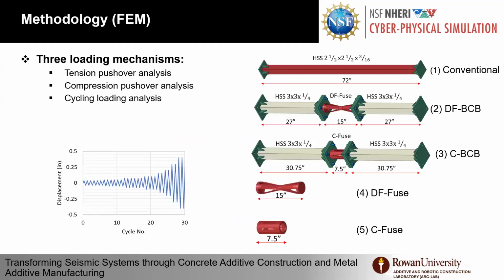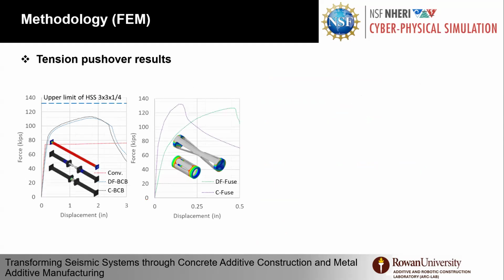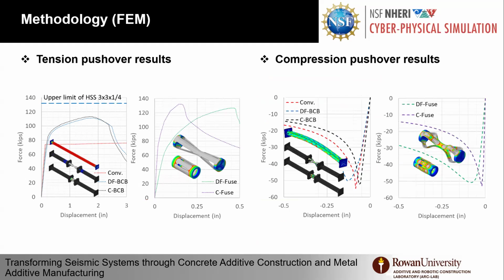So as you can see here, we have 5 different numerically tested specimens. The first one is just a regular conventional brace. The second and third are the hybrid ones, with either a double funnel or cylinder fuse in the middle. And the other ones are just the cylinder fuse itself, under tension pushover, compression pushover, and cyclic loading. So in tension, as you can see here, our hybrid systems surpassed the conventional, but we are still under the limit of the capacity of the protected element and outer element, so we are in good shape. On the compression side, we get really close to the compression capacity of the conventional ones.